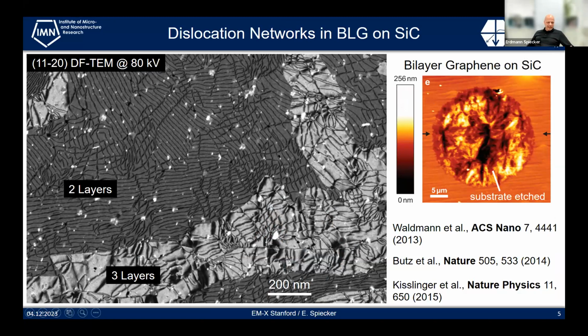And it was, of course, extremely difficult to make these plan view TEM images because you have to finally remove the silicon carbide from the back. And this can only be done by etching and laser-assisted etching, and you have to keep the graphene intact. But finally, it worked out, as you see here from the AFM image and the TEM image. And what we realized, it's full of defects, which was not expected.